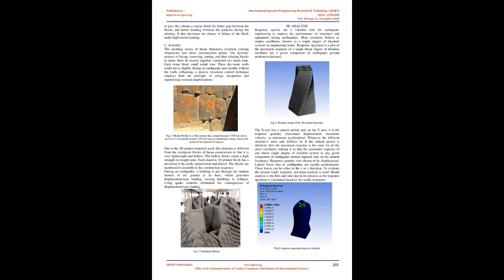Materials used in fused deposition modeling like polylactide, acrylonitrile styrene, polyethylene terephthalate glycol filament are all susceptible to higher temperatures. In contrast, selective laser sintering uses a nylon-based powder with a higher strength-to-weight ratio than the materials mentioned above. After severe considerations and analyzing much material, finally, a nylon-based fine powder mixture was selected because of its strength and